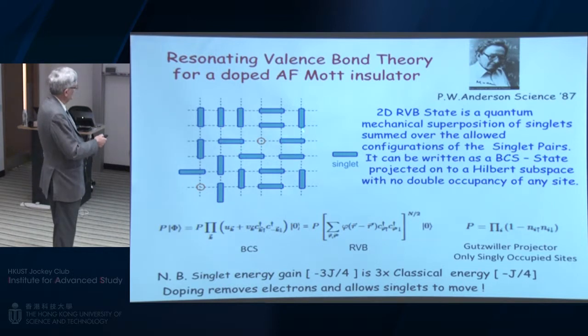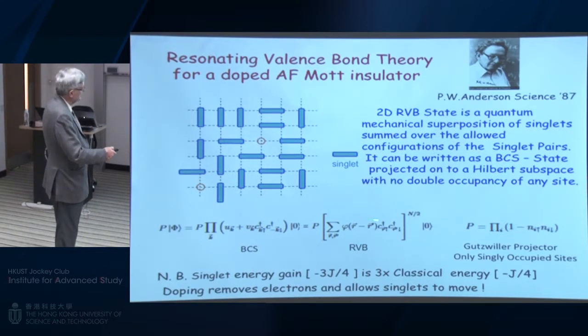So if you had a situation where you had essentially a network of these singlets, but then you make a superposition of all the different possible arrangements of singlets, and then you take particles out, there is a close analogy between the BCS wave function when we force all the electrons to sit no more than one electron on the site, and this arrangement, this resonating valence bond of singlets. So looking at it this way, this gives you a hint that the magnetism in this material here may be making it on the verge of superconductivity.